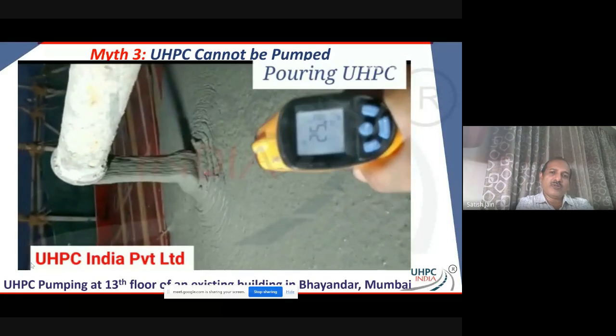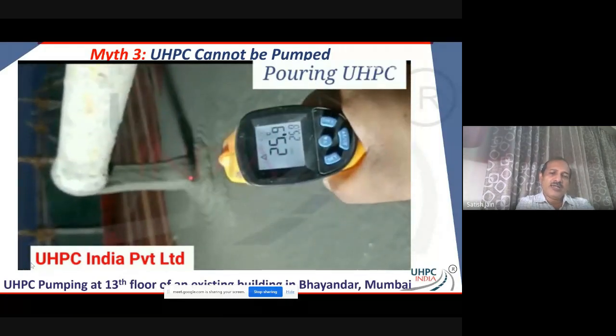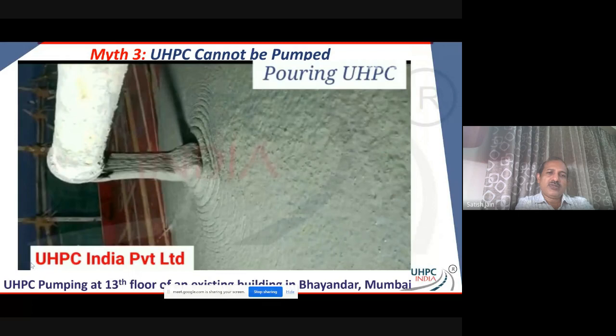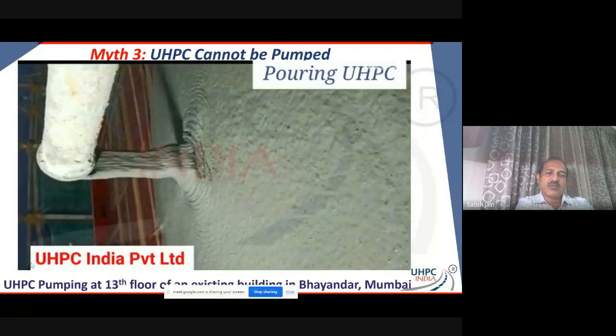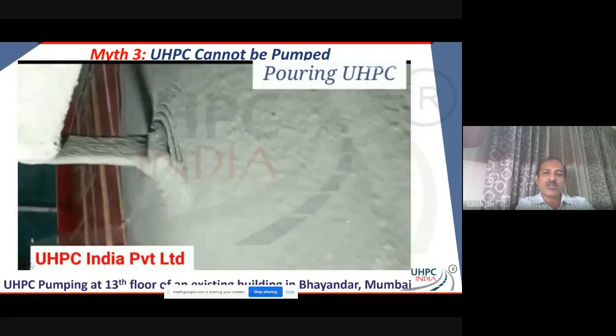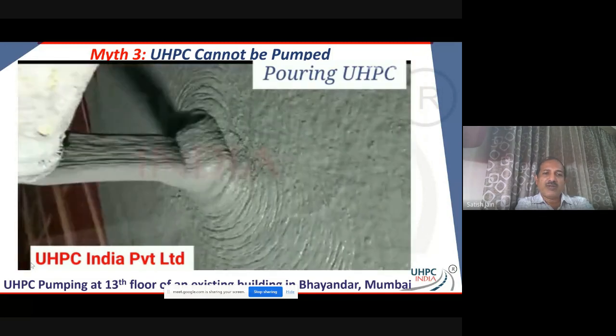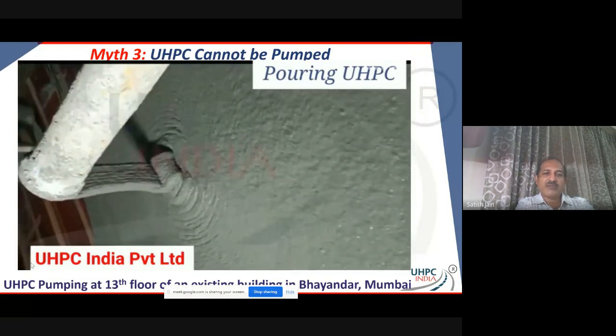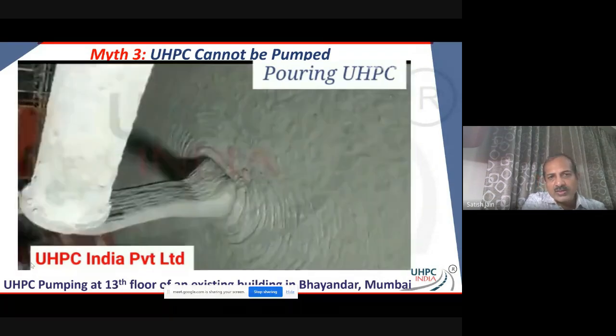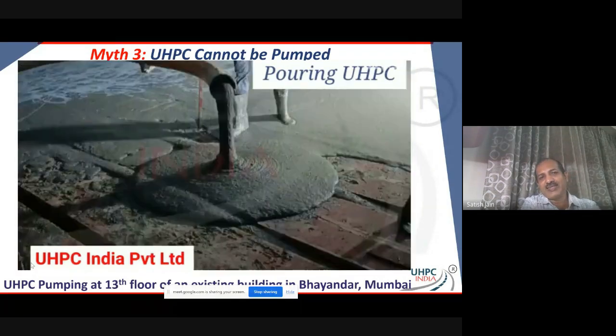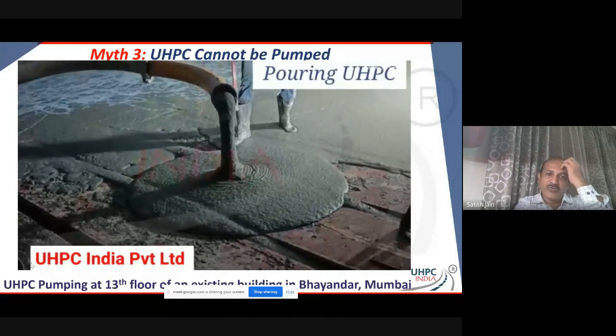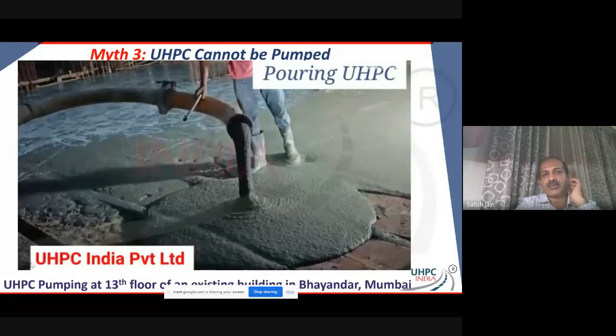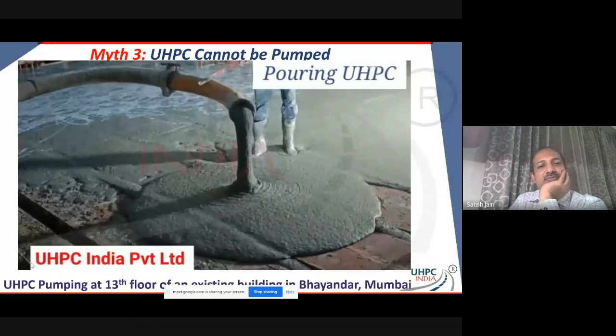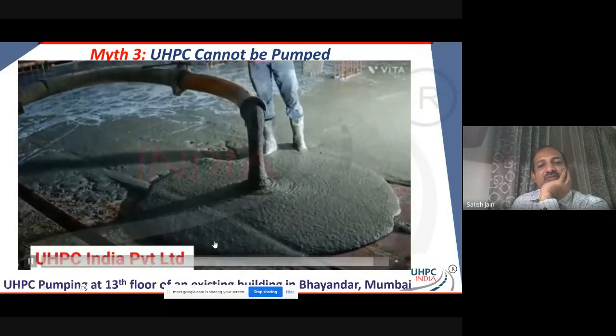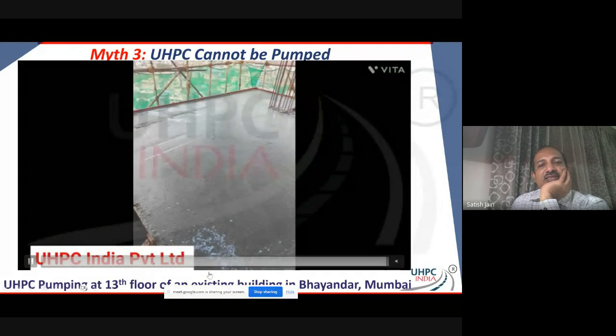And you can see that in a video over here. The temperatures are low, about 25, 26 degrees Celsius. It's just so nicely coming out. You can imagine this UHPC has a huge amount of steel fibers in it, the microfine steel fibers, and it's still flowing out consistently. That's how beautiful it is. You just don't have to do anything.